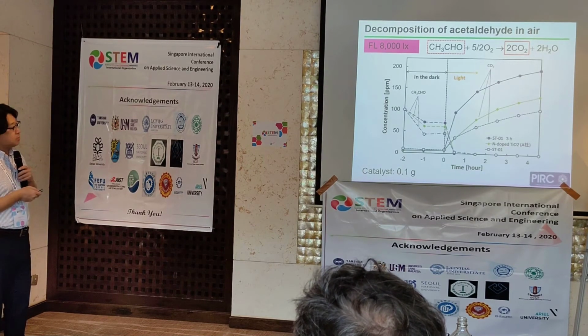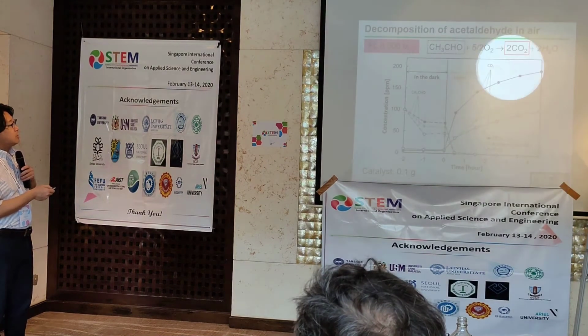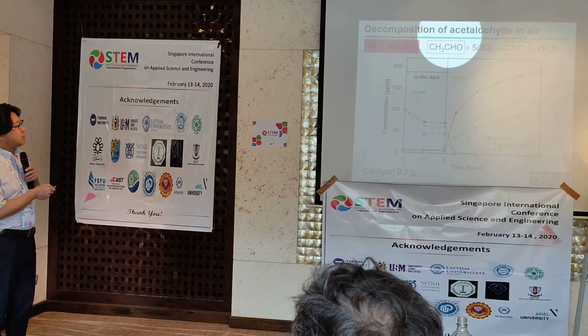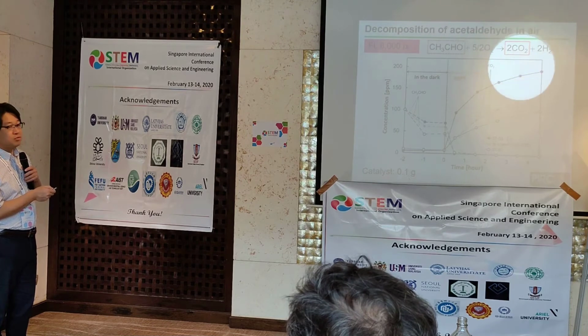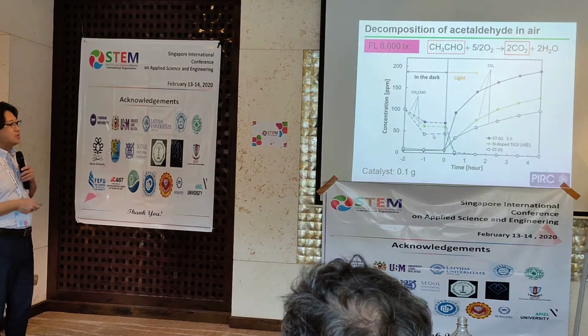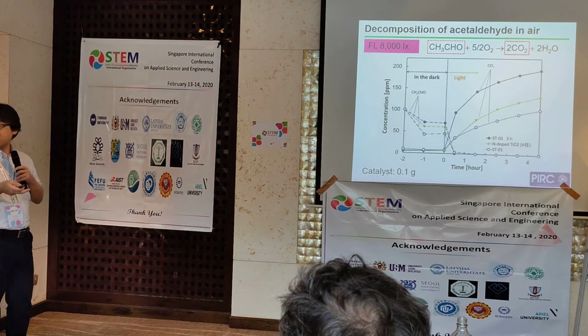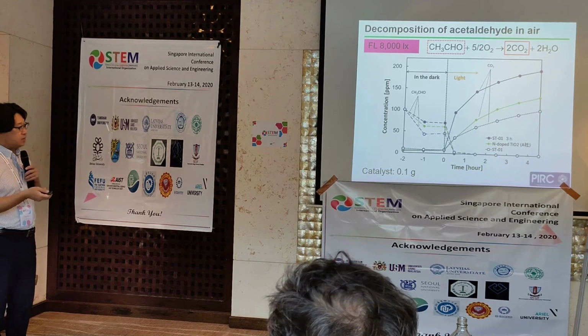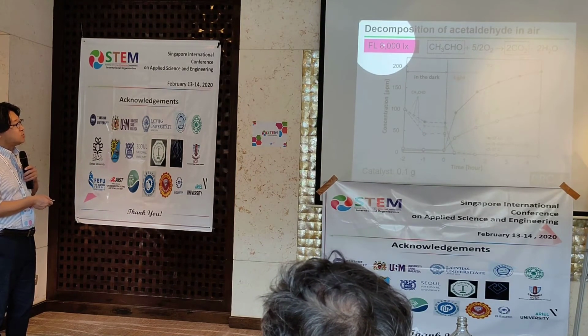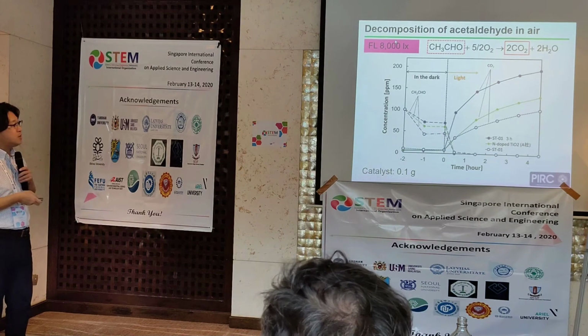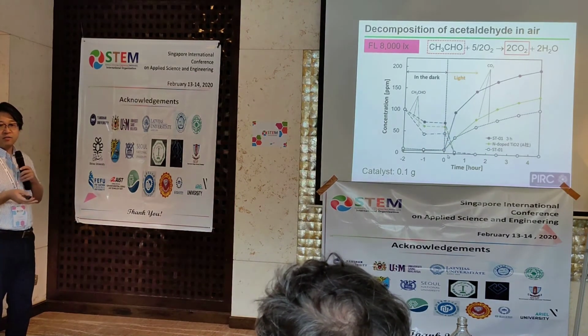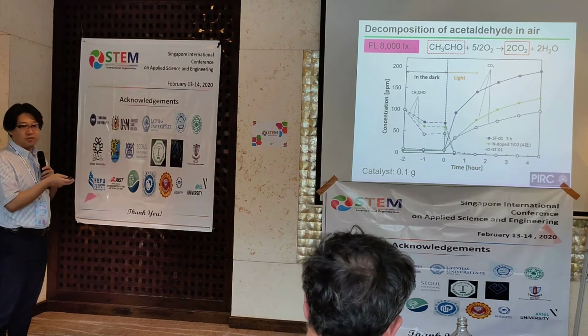So this is the result. This is the equation of acetaldehyde decomposed to carbon dioxide. Please see the molecular ratio, 1 to 2. In this dark region, acetaldehyde just adsorbs on this material. At this point, light is irradiated. In this case, we used a fluorescent lamp like this one. Then the acetaldehyde concentration goes to 0 immediately. That means photocatalytic decomposition occurs in this reaction.